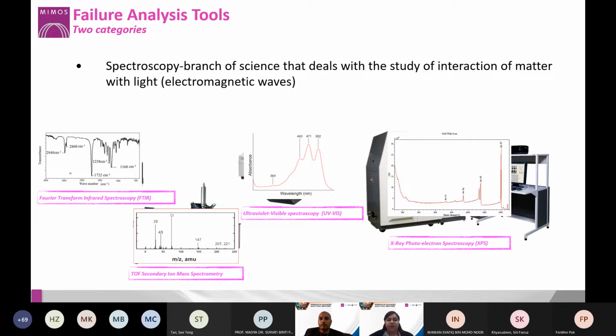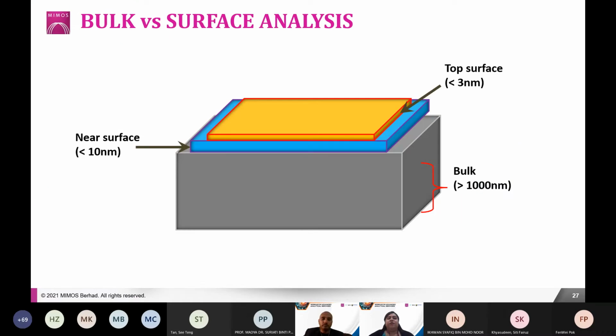So these are the type of spectrum which you can obtain from this particular analysis. So what is the difference between a bulk versus a surface analysis? Sometimes you want to see in bulk, it doesn't matter, you want to identify the element at the whole bulk, I mean the whole sample. But some of you have grown thin films only at the top surface. Maybe you have grown some aluminium on the top, which is less than 3 nanometer, and you want to identify it. So which is the proper equipment which you need to use?